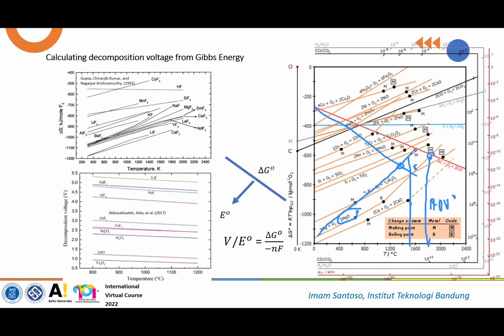We put the reagent in vacuum, so the reduction can take place at low temperature, and yes, we successfully produced magnesium from magnesium oxide, and we published it in a paper. So that's an example of using the Ellingham diagram to predict whether a reaction like reduction or oxidation happens.